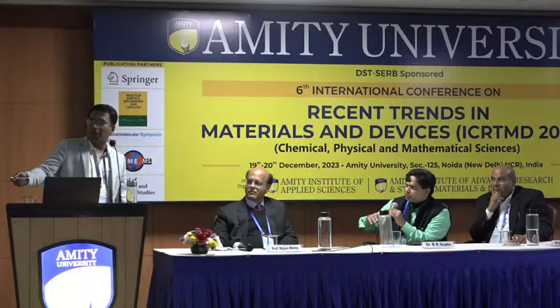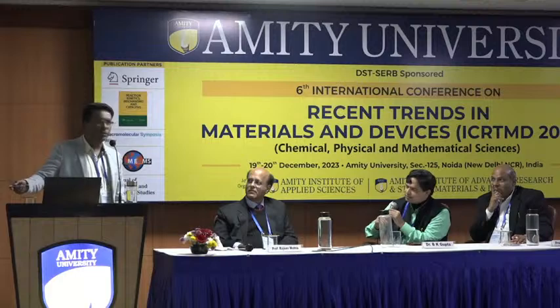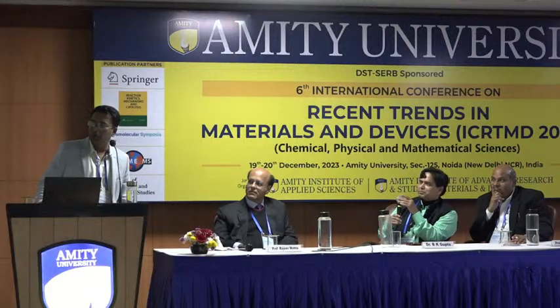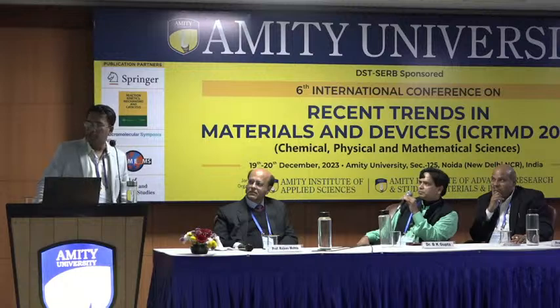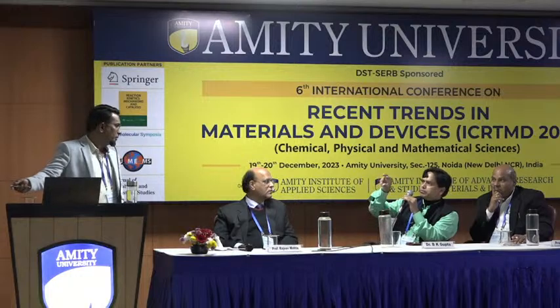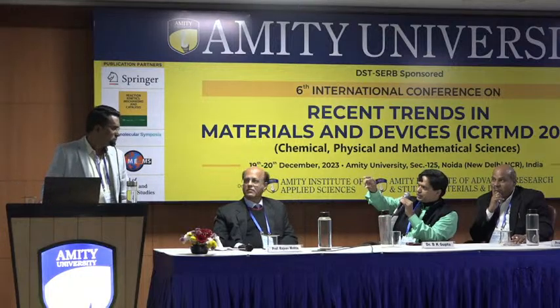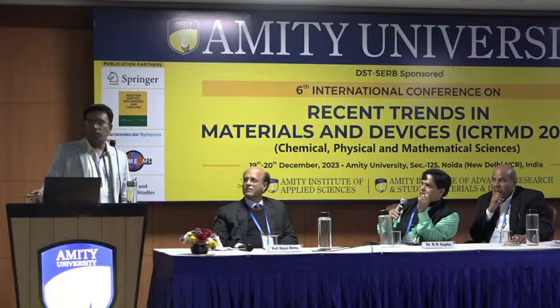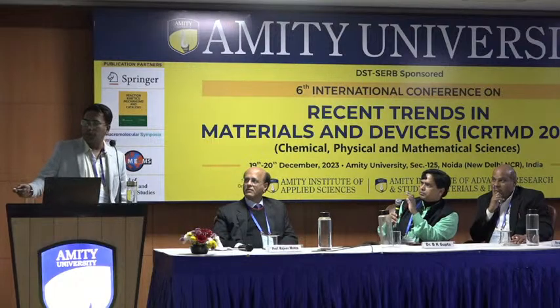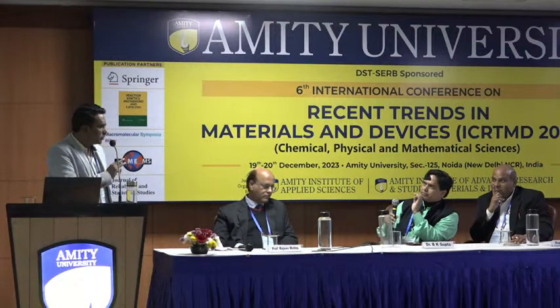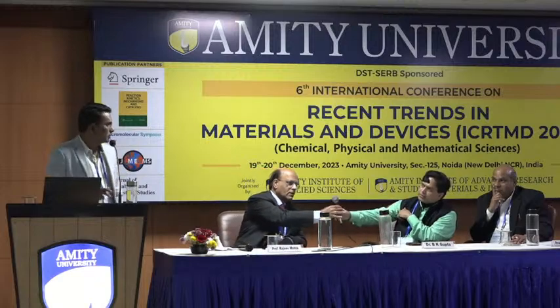You mean to say why this is changing, yes? Yes, this is changing. That is what we observed in the quantification of the carbon monoxide. What we observed is that when we change the doping concentration, we get a higher percentage, maximum site selective. What we are saying is that this chromium dopant is actually tuning the electronic environment of the oxygen.